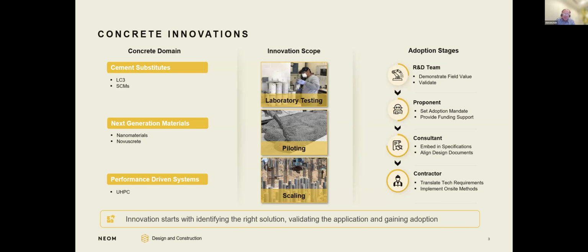We had some experience with nanomaterials, so interesting that you've got work and research on graphene. We've used and added graphene. We have experienced some real complications in using it, particularly in developing a homogeneous mix for application. When we were getting good mixing, we were seeing something like an 8% improvement in compressive strength with the applications we were using it for. But we were also seeing, where we weren't getting good mixing, a reduction in compressive strength because of the clumping of the material and the kind of weak spots that you were creating. So potentially higher risk, and we haven't continued to pursue that work.